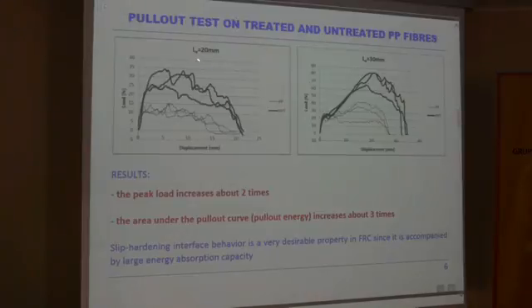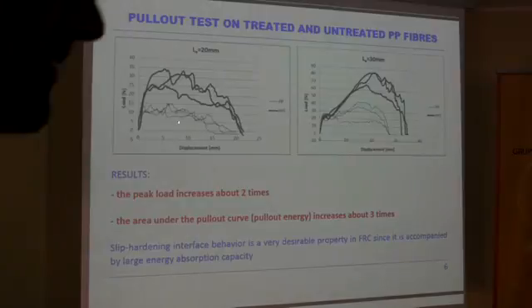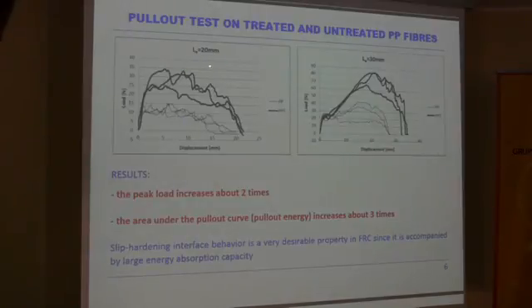And then these are the results of experimental tests on treated and untreated fibers with different embedded lengths, 2 centimeters and 3 centimeters. We see that the solid and thicker lines concern the response of treated fiber, whereas the thinner lines are the response of the untreated fibers. What we can observe is, of course, that the pull-out force increases with the embedded length. So from 2 to 3 centimeters, the pull-out load increases remarkably. But we also saw that the peak load, the maximum pull-out load, increased about 2 times between treated and untreated fiber for both embedded lengths.